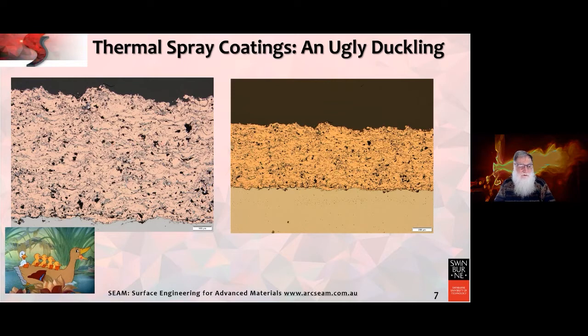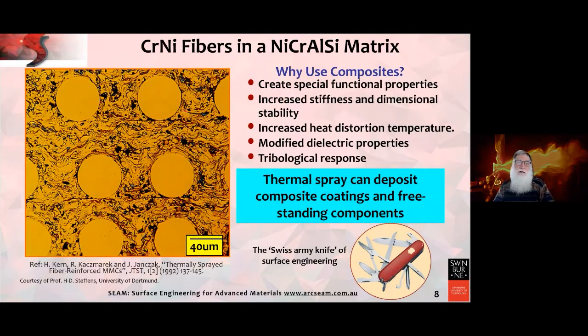So what I'm going to try to describe here is that we really have an ugly duckling here. And I'm going to say that this ugly duckling, that these structures are in fact beautiful. And I will talk more about the features of these microstructures just in a little while. So here are some more structures, for example. This is of chrome nickel fibers in a nickel chrome aluminium silicon matrix. And what you can see is a thermal spray coating. And within that, we have embedded these fibers. This is quite old work, but it shows that thermal spray coatings can create amazing structures.